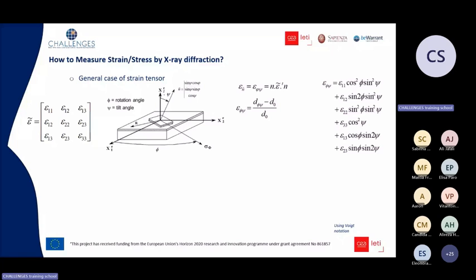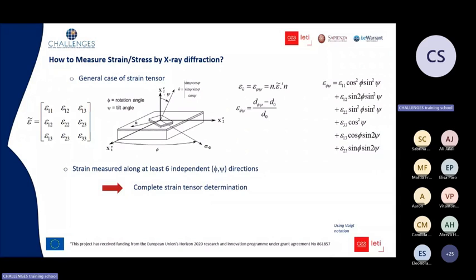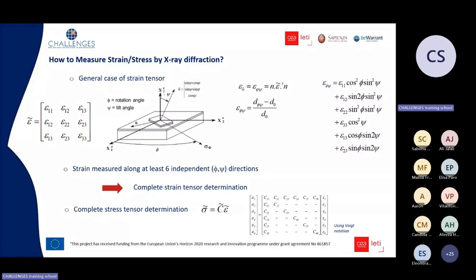This is very interesting because it means that with X-ray diffraction, if we are able to measure different directions, at least six independent phi psi directions, we are able to measure the complete strain tensor. So we have a complete strain tensor determination thanks to X-ray analysis. And if we apply to this strain tensor the elastic constants, the full elastic constants of the material, for the very general case, we are able to calculate the complete stress tensor. So this is the force of X-ray diffraction for stress analysis.